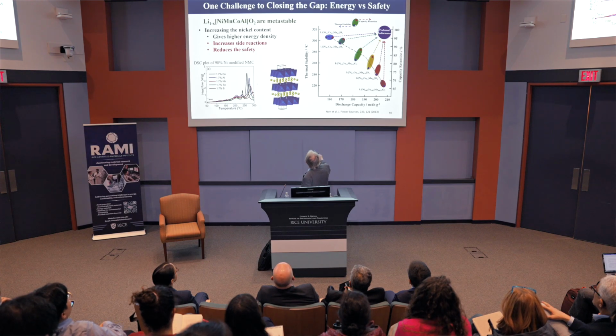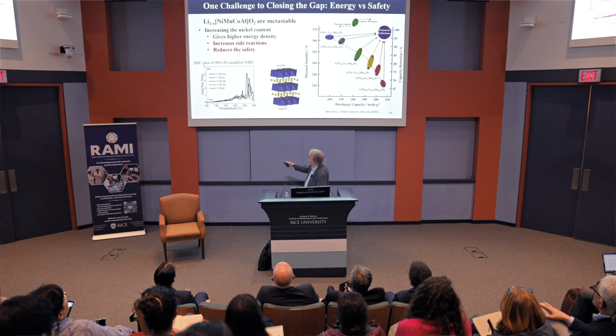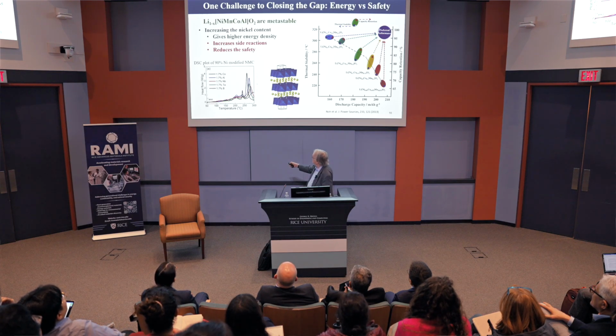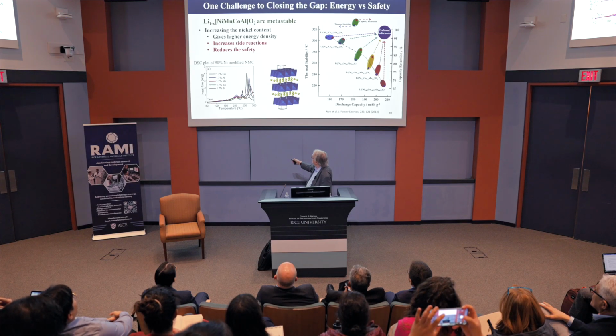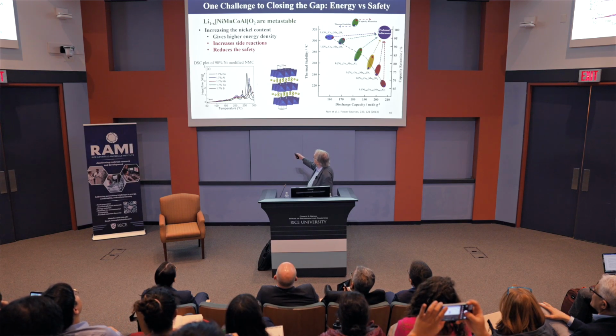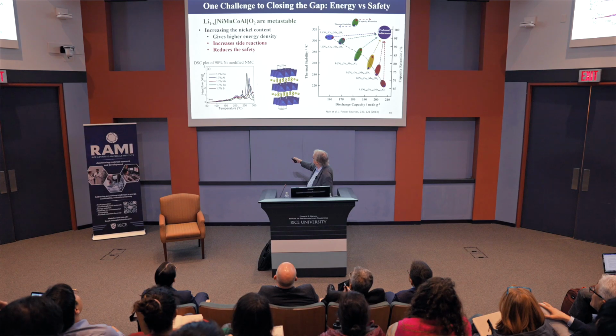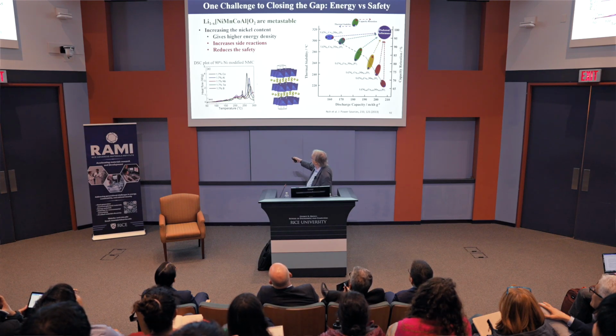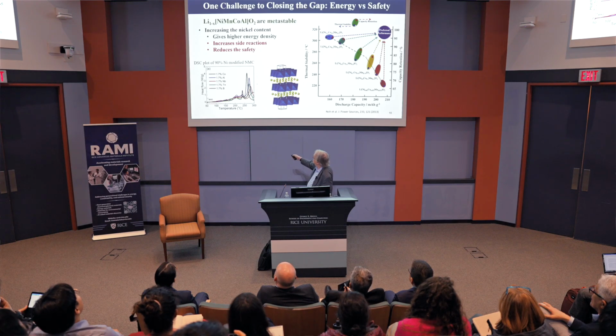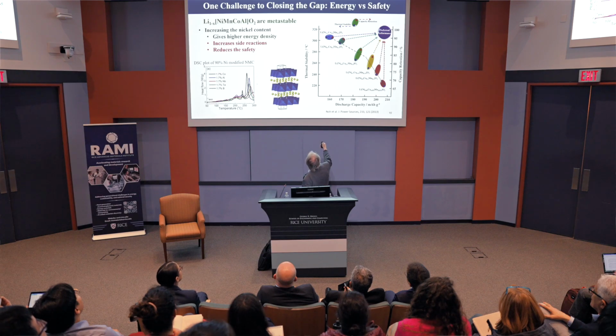But this vertical axis now gives the thermal stability. What do we mean by that? It means if we do a DSC study, like here, and just heat up the NMC and the electrolyte, you see we get exotherms in here, and these materials start decomposing about 200 degrees Centigrade. The best ones are about 300, and the best one here is a niobium modified one. But this plot has thermal stability on this axis. The more thermally stable, the less lithium, the less energy.